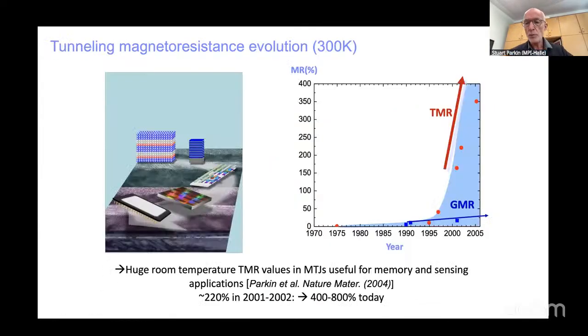What Jagadish Moodera showed earlier was that he saw a few percent change in tunneling magnetoresistance at room temperature using amorphous aluminum oxide, but those are very tiny effects. So this enormous increase in tunneling magnetoresistance that we demonstrated, and there are even larger values today, makes it possible to use tunneling magnetoresistance devices not only for sensing data in magnetic disk drives, which happened in the mid-2000s, but also for another type of device, a magnetic memory device, where you store information in the direction of the magnetization of one of the layers in a magnetic tunneling junction.